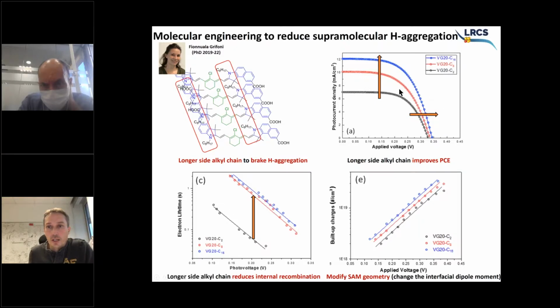When you make a long alkyl chain, in terms of devices you will see first, of course, it becomes more transparent, but secondly, you improve the photocurrent and you also increase the cell photovoltage. Increasing the side alkyl chain also tends to increase the electron lifetime, which means that it reduces the non-geminate recombination processes inside the devices. So we have a better charge collection efficiency of the carriers, and it slightly modifies the cell capacitance, which means that it slightly modifies the self-assembled monolayer geometry.